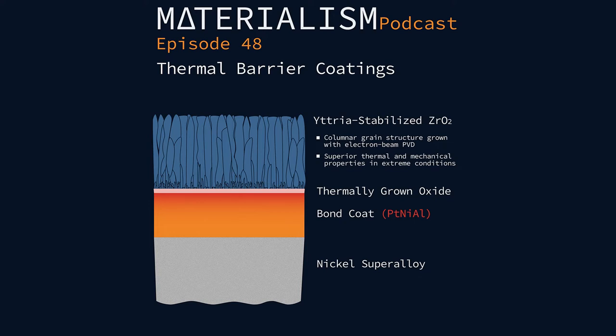There are two ways that they use in industry. You either do electron beam physical vapor deposition, where, imagine an SEM microscope where you have a beam of electrons, except that now instead of hitting a target that you're visualizing, you increase the voltage, and there's a lot more going on. It hits a source material, which you're trying to volatilize, and it can eject a plume onto a material. It's as simple as that. It works great if you have a really small component. It's expensive, and it's really hard to scale into large areas. But for small things like blades inside of a turbine, you can do this and get really high quality films. And then the other way is plasma spray.